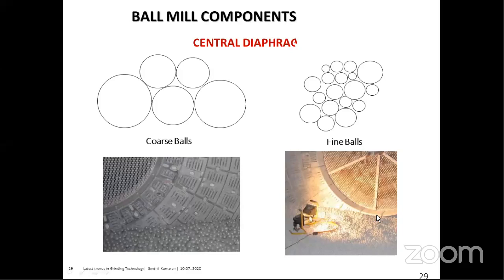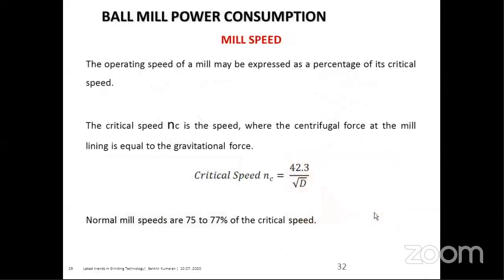We fill only up to 30% of the mill volume, which we have discussed. Critical speed is the speed where the centrifugal force at the mill lining is equal to the gravitational force. The critical speed equation is 42.3 divided by root of D. The normal mill speeds are 75 to 77% of the critical speed.